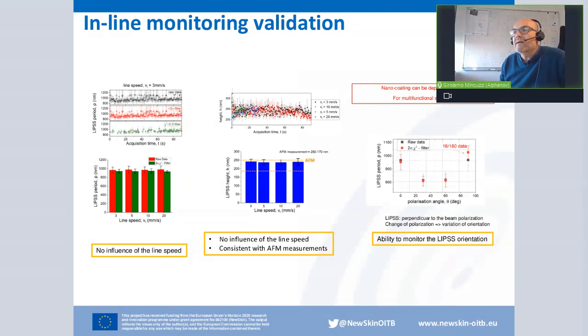The inline monitoring that we use has been validated. Here you see the signal relative to the period, for 3 millimeters per second, and for different linear speeds of the roll-to-roll system. As you can see, the system is quite stable. Filtering has been done to improve the signal, and then implemented in the machine.